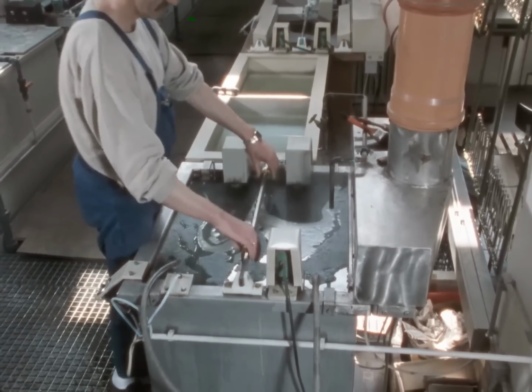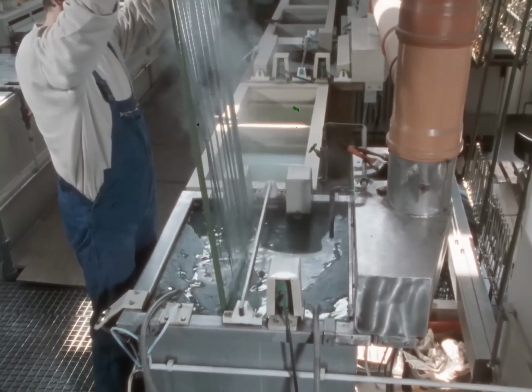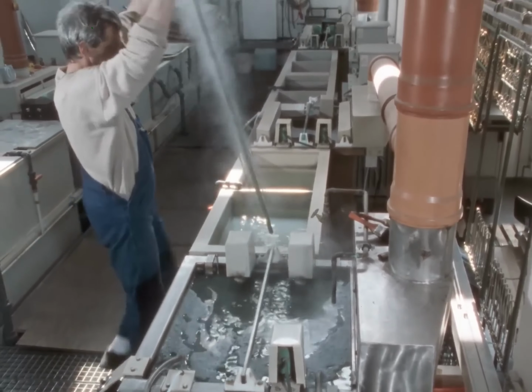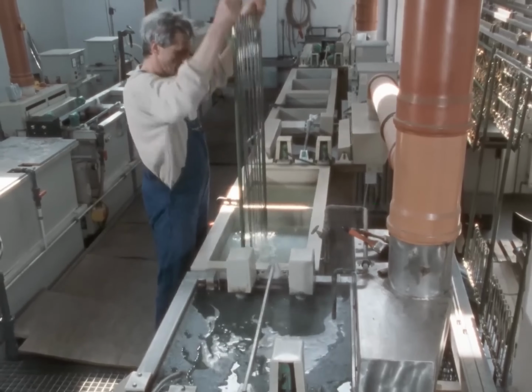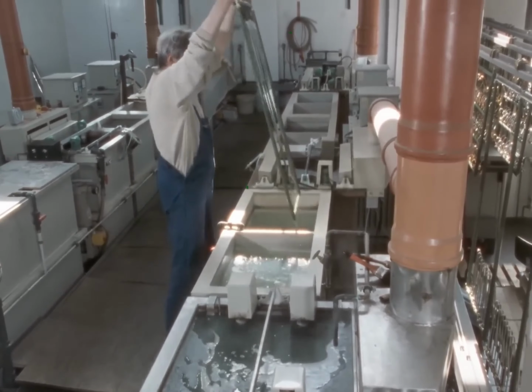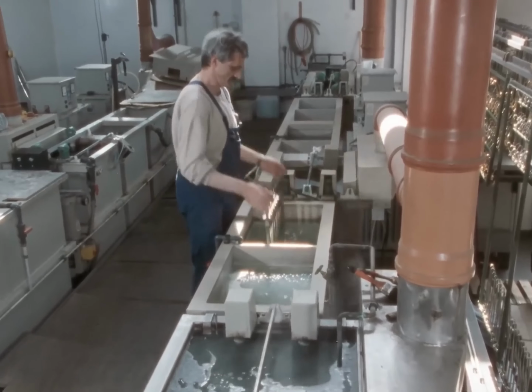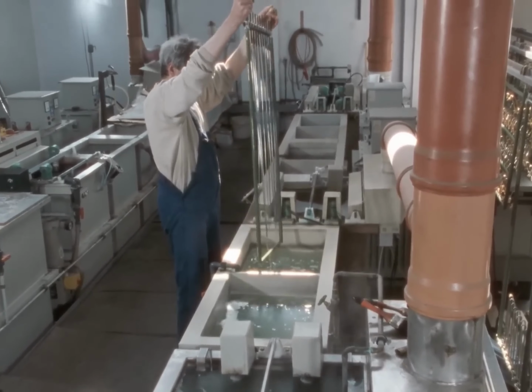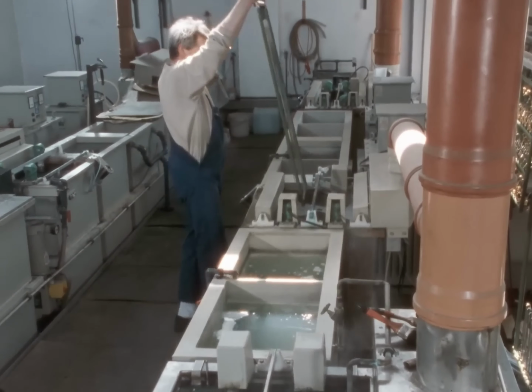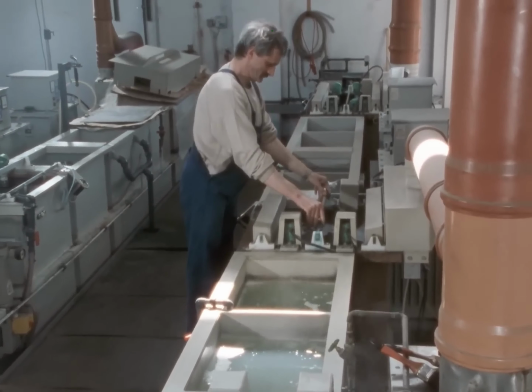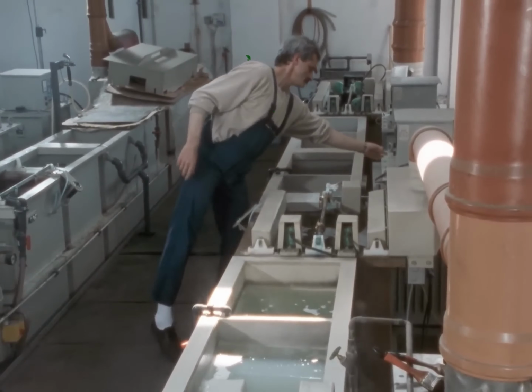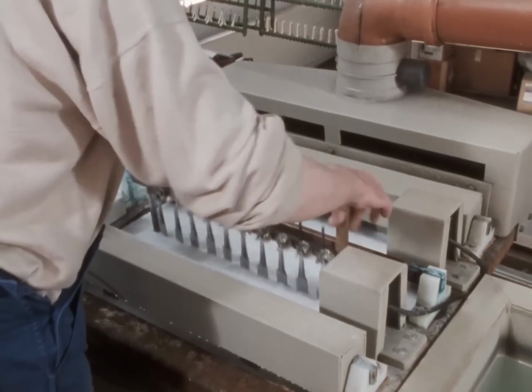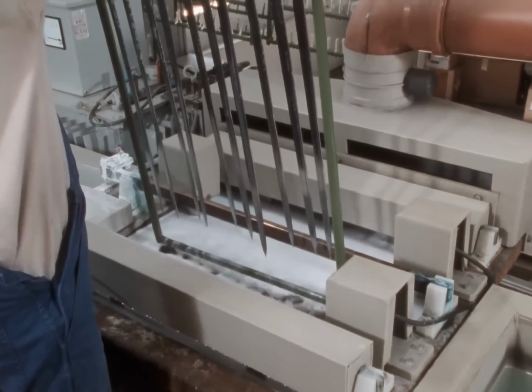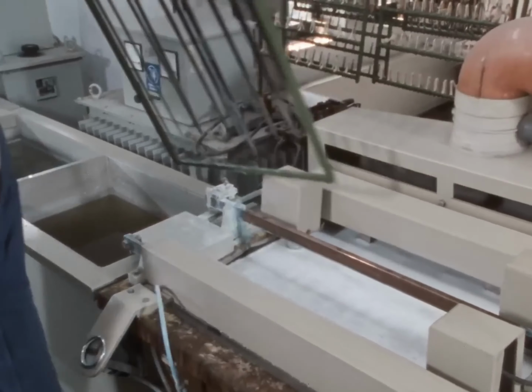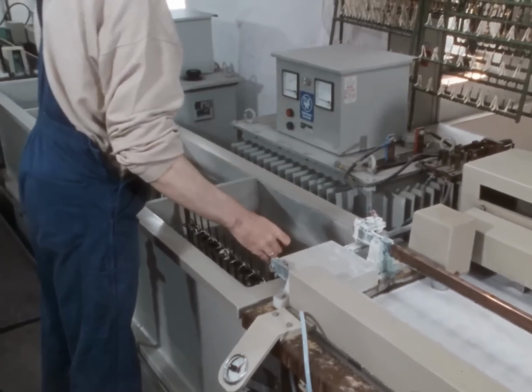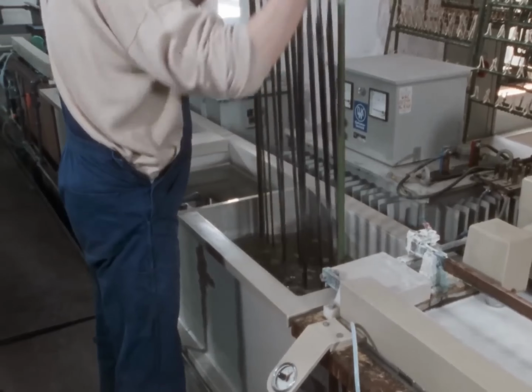The plant itself is relatively new, installed in 1991, and it runs the blades through 9 separate baths in order. First comes ultrasonic cleaning at 80 degrees Celsius, using sound vibration through the liquid to shake loose any residue clinging to the surface. Water rinse baths follow, washing that residue away completely. Then, an electrolytic anodic degreasing bath strips away the last traces of oil or grease, using an electrical current running through the solution to do chemically what a simple wash alone couldn't.